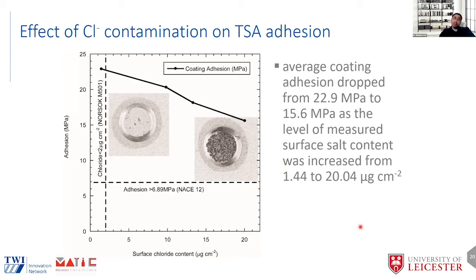Not only that, we are also seeing the nature of delamination or disbondment that might happen due to pull-off. In this case, we are seeing that the coating has failed cohesively. And in this case, we can see that the coating has completely come off from the substrate at fairly high chloride content. Typically, one would want to keep the surface chloride content, following NORSOK M-501, to less than 2 micrograms per centimeter square. So that's a little bit about the effect of surface preparation and what we need to be careful about in terms of surface.